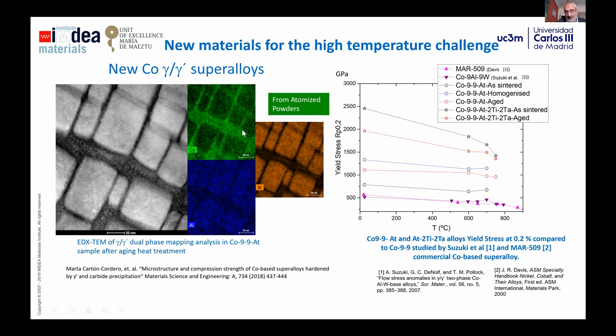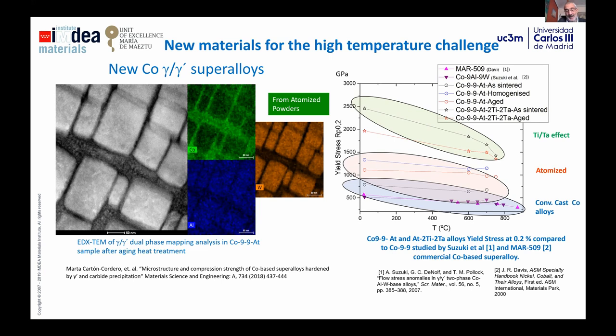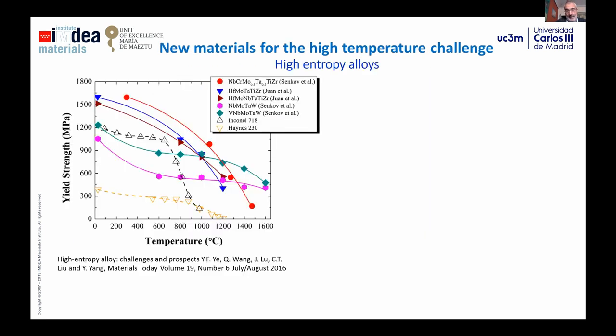Here we have the results obtained for this alloy in conventional cobalt-based casting alloys, but also using casting for this specific superalloy. But by powder metallurgy, using fully atomized powder, we can improve the yield stress much better as a function of the temperature. And even by addition of different alloying elements, by mixing the powders and by mechanical alloying through the atomized powder, we can also reach much better properties. But in the last times,